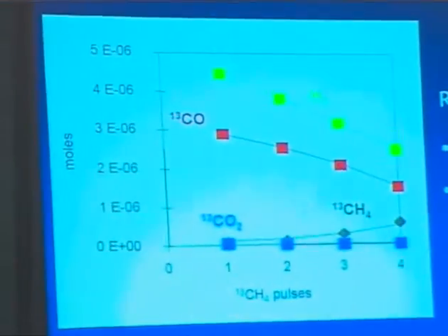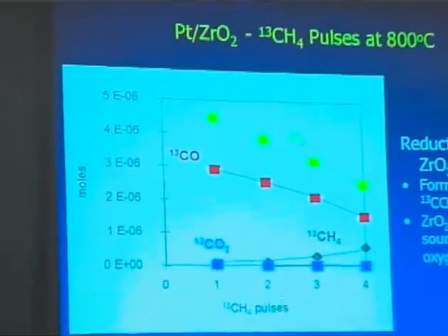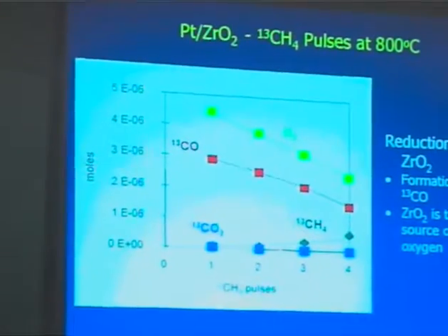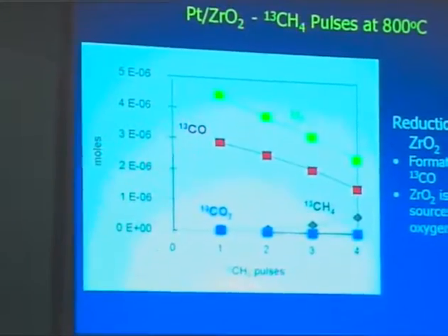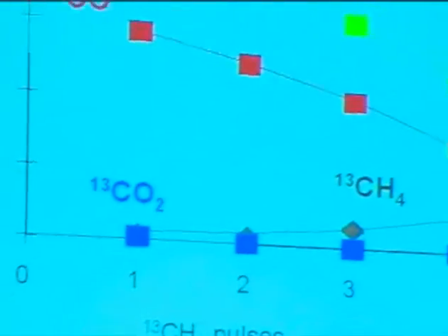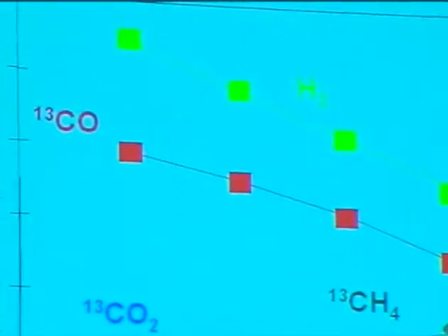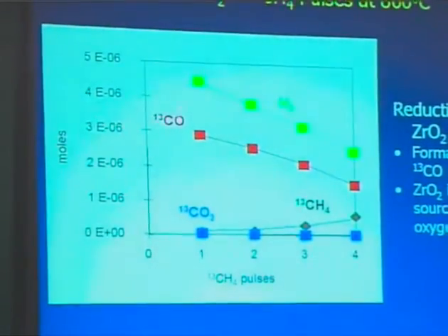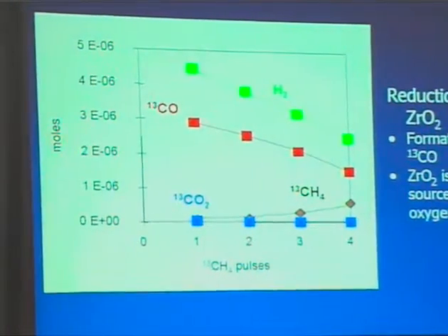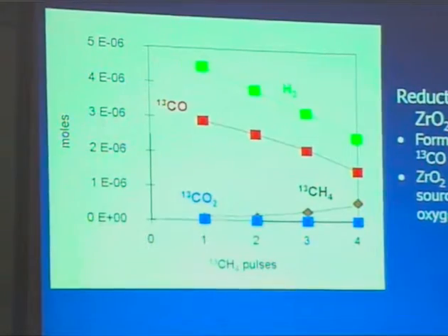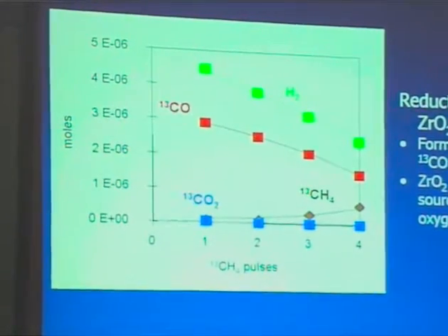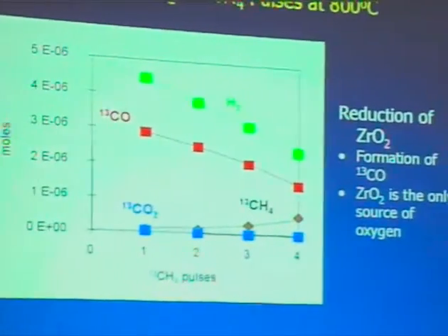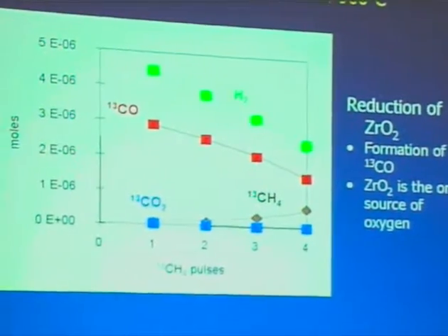How we verified this mechanism on the different supports that we had studied was the first thing we looked at: carbon-13 labeled pulses of methane. We did some isotopic studies, and what we found is that when you take platinum zirconia and you pulse carbon-13 labeled methane at 800 degrees, you see the formation of hydrogen, but you also see the formation of a significant amount of carbon-13 labeled CO. Zirconia is the only source of oxygen in the system, and therefore that oxygen must be coming from the support.